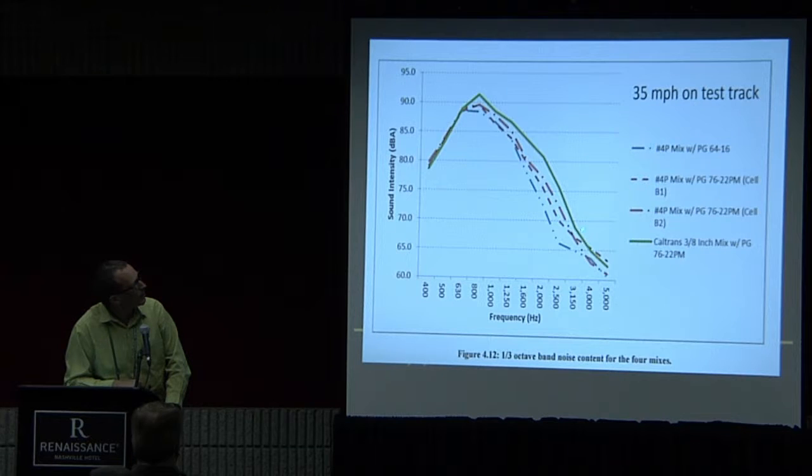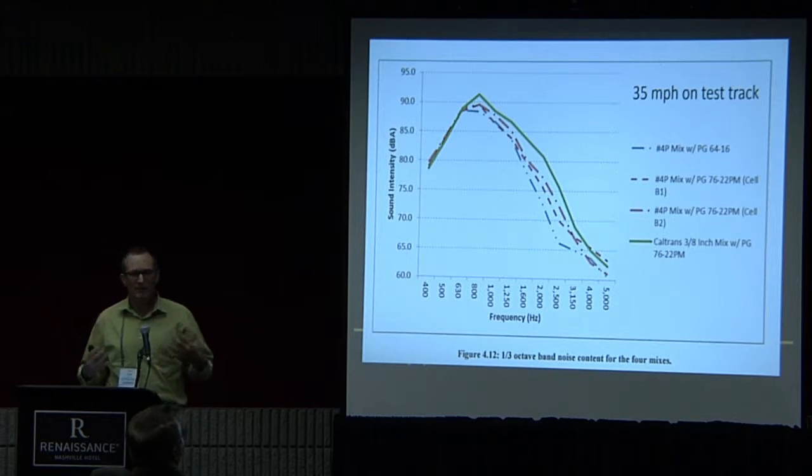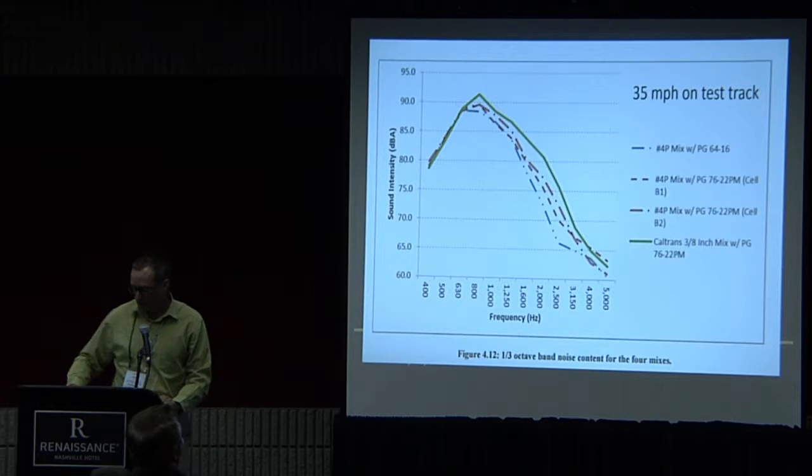But here's our traditional 9 millimeter mix, which is already fairly small, 3/8 inch, and you can see that the shift happened. What was interesting, and we haven't completely figured out, is we didn't get the shift so much on the lower frequencies where we expected it, but we got them on the higher frequencies, which is more the air pumping. We haven't completely figured that out, but we definitely got a noise benefit.